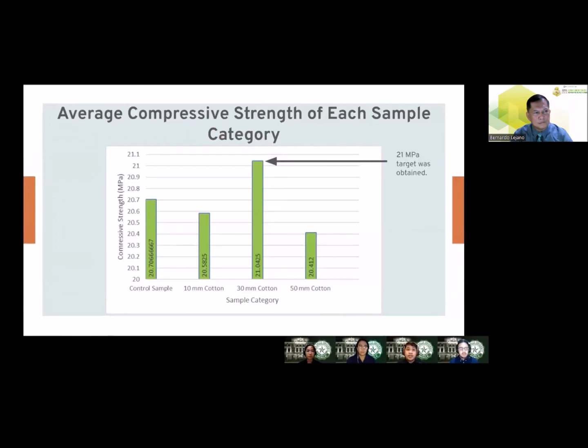The results show that the use of 30 mm cotton fibers yielded the highest compressive strength, while the use of 50 mm yielded the lowest. Though the differences between the cases are minor, it is to be noted that the 30 mm case reached the 21 MPa target of the study.